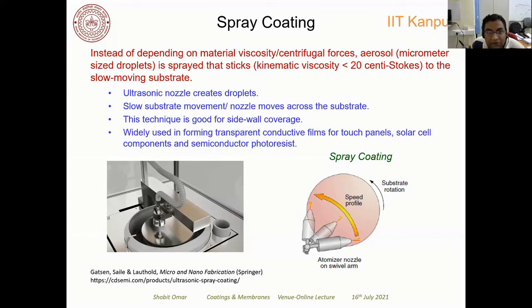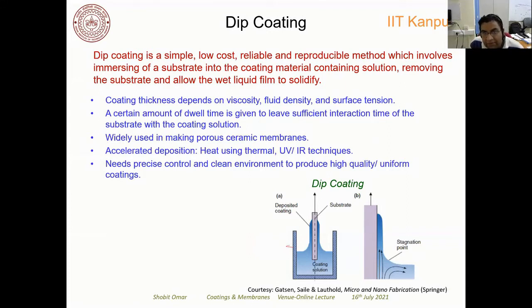Conductive film for touch panel, solar cell component, and semiconductor photoresist. Then this technique, I guess everybody is aware of. It's basically a very simple technique. It's called dip coating, where you take the component and you dip it inside the liquid and you put it for a certain period of time to allow sufficient interaction between the substrate and the coating solution. And then you take it out, withdraw it at a particular speed, and then you will form a thin film over the substrate. So this technique is very widely used in making porous ceramic membranes. Okay, and of course you have to dry the coatings that will form, and that can be done through thermal heating or using ultraviolet and infrared rays technique.